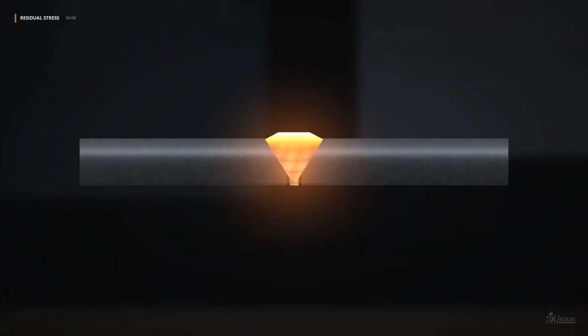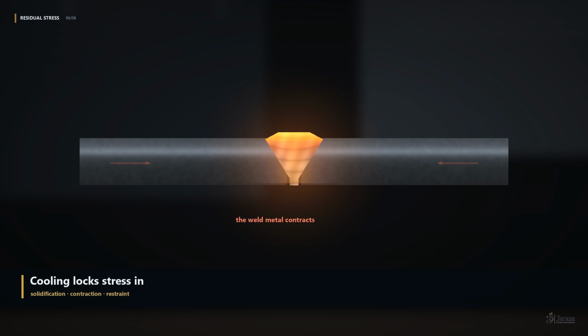Watch what happens as the weld cools. The molten metal solidifies and then contracts, but the surrounding steel will not let it. The plate pulls in. The joint closes on itself and rotates, angular distortion, and the whole assembly shrinks along the weld. When it finally stops moving, the metal is locked in a fight with itself.